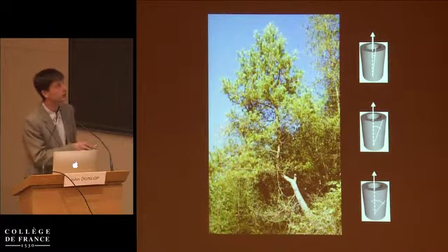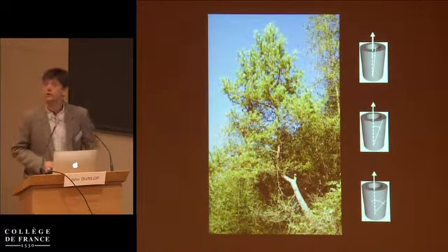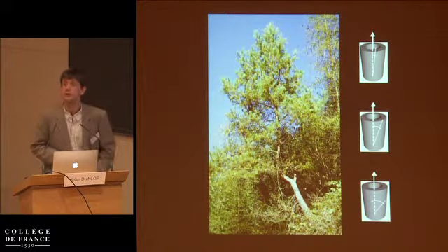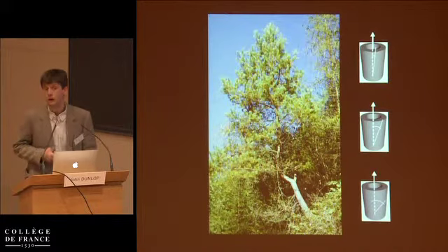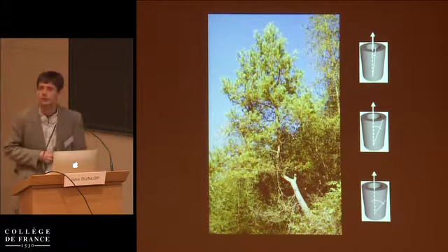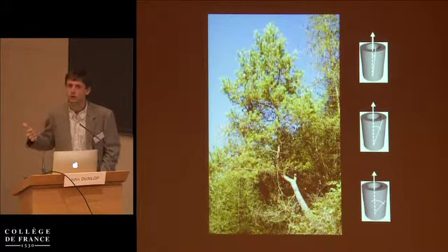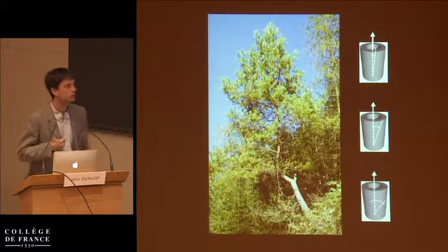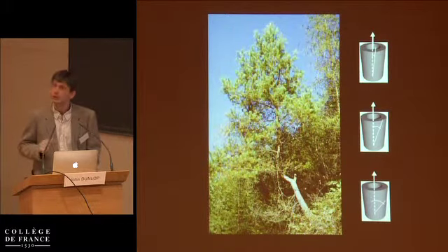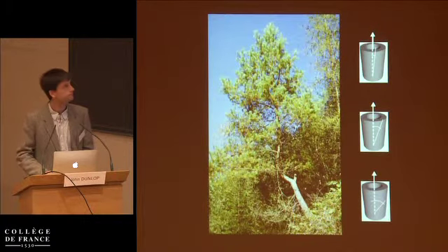And as a consequence, you find smaller microfibril angles, so stiffer material, being produced in the newer wood, or in older specimens. And this is quite interesting because this is one control parameter that the plant can use. This is just changing angle, and you can get quite a large change in mechanical properties.